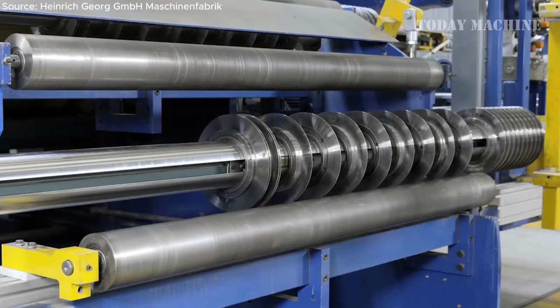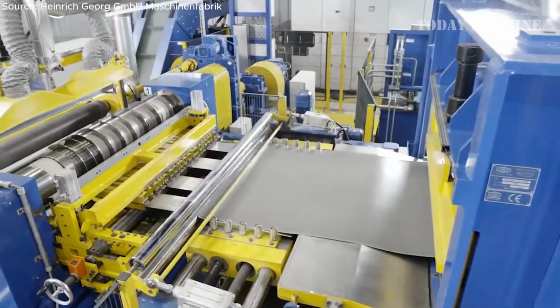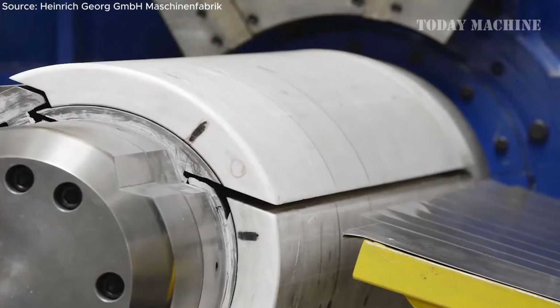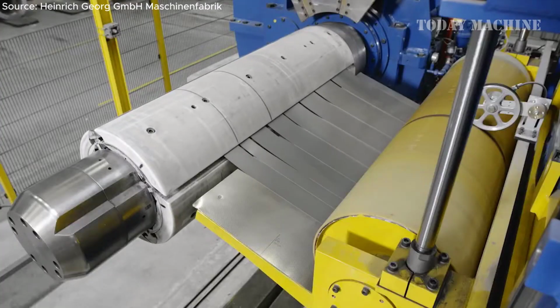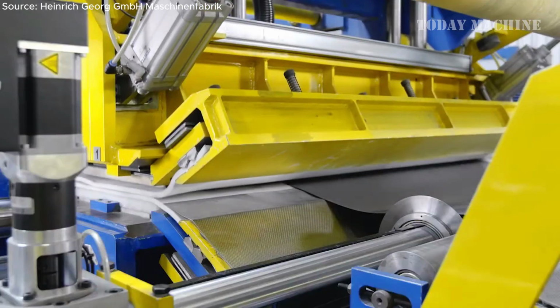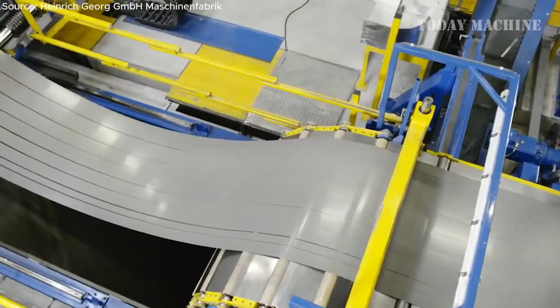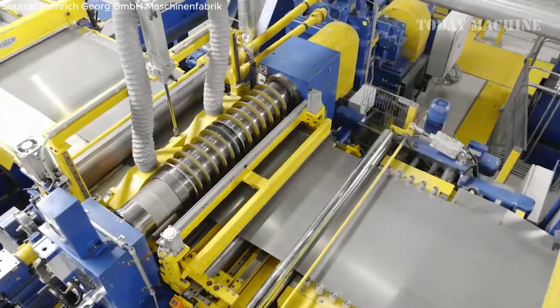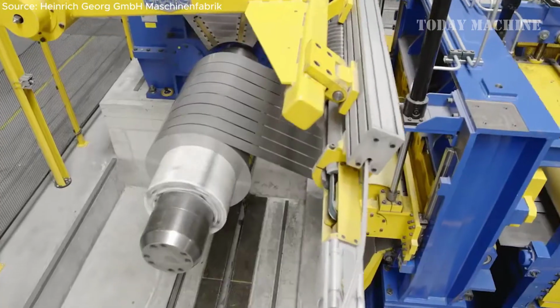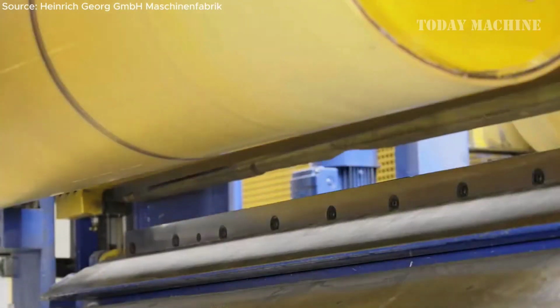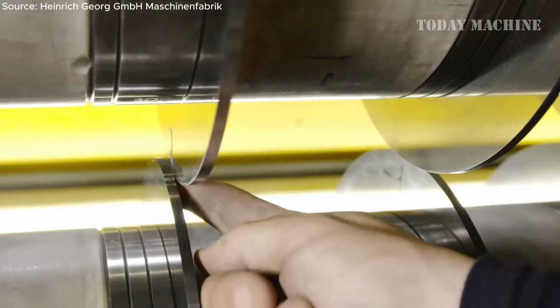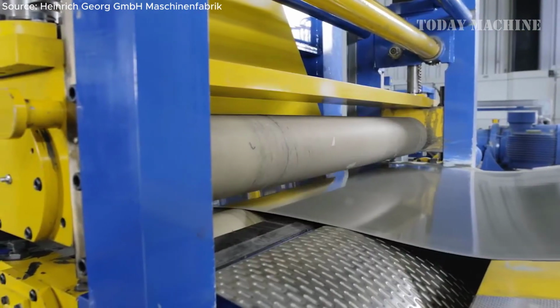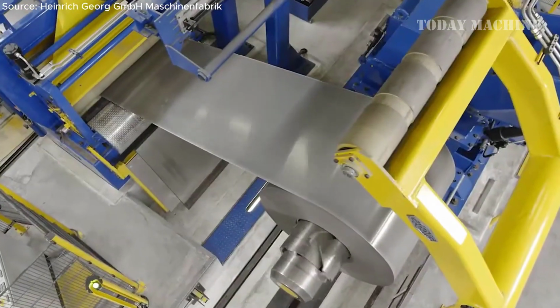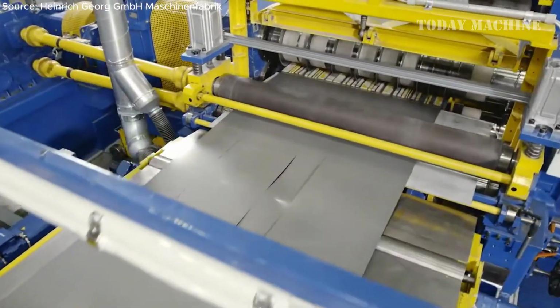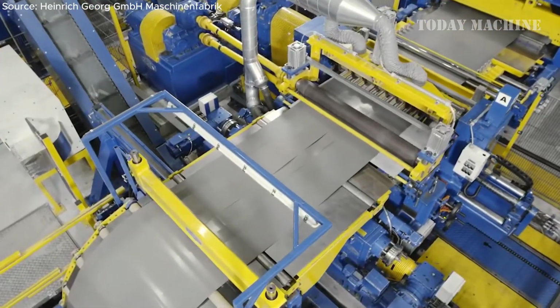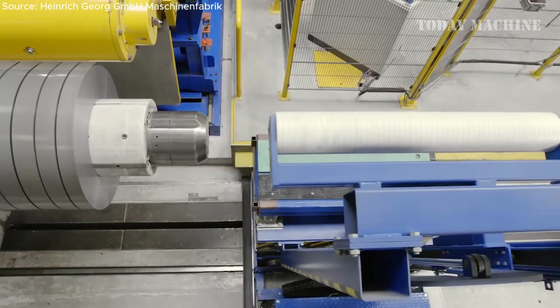The process begins by loading a master coil onto the uncoiler. The metal strip is then fed through the slitter, where rotary knives make precise longitudinal cuts, producing strips of desired widths. These strips are subsequently rewound into coils by the recoiler, ready for downstream applications. Additionally, the line is designed to handle material strengths exceeding 1,800 N per square millimeter and yield points up to 1,200 N per square millimeter, ensuring versatility across various metal types.